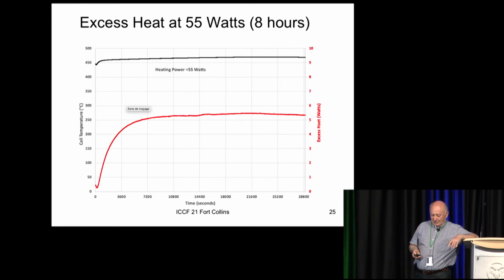So this shows you that the experiment lasts for 8 hours. And you might ask, why did I stop after 8 hours? Because I increased the power to go higher, to get more heat. And then the heating filament broke, and that was it, you know. I'm sorry, it didn't work.